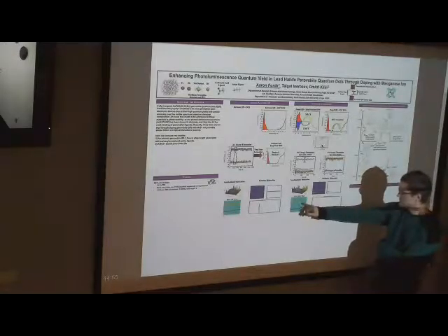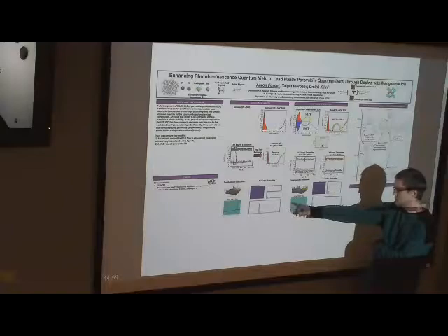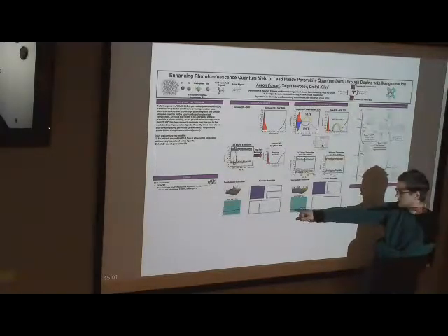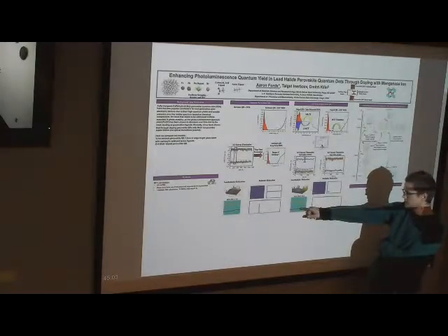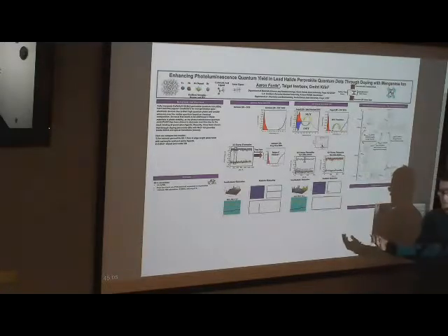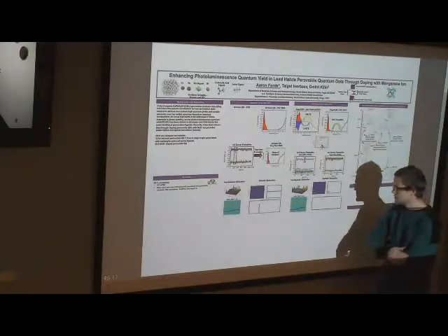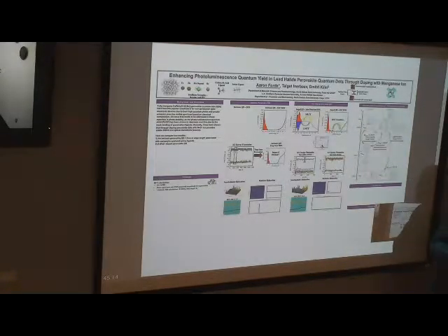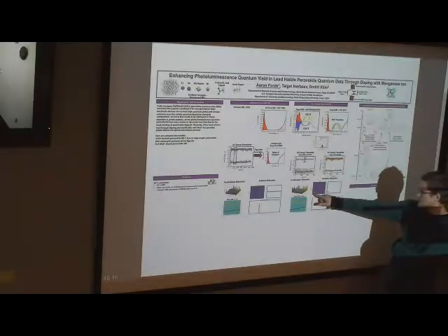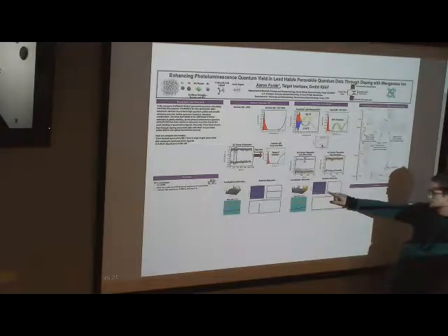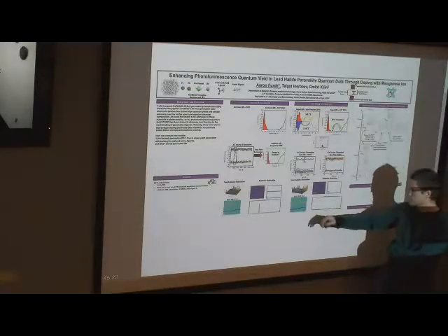And then here is just another excitation from HOMO minus 23 to LUMO plus 13. And in this system, it appears instead that the hole and the electron relax at about the same time, on the same order of magnitude of time anyway, to the gap. And we see that in the excited state before it relaxes to the HOMO-LUMO, there's quite a bit of emission coming from as it relaxes to the gap.